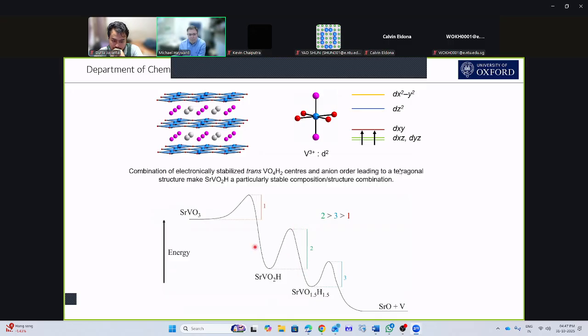the system. And so if I add enough energy to get over barrier 1, I can end up making SrVO2H. But if I add enough energy to get over barrier 2, I've also got enough energy to get over barrier 3. So I can never stabilize SrVO1.5H1.5, because basically SrVO2H is too stable.